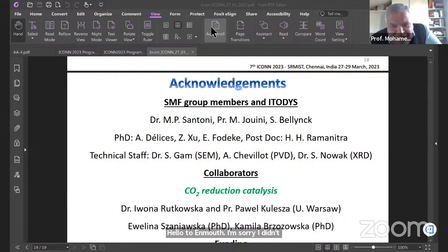Yes, palladium. We use palladium because this was a first work on this kind of electrode, and it was just a proof of concept. We can use any catalyst, but the only problem is to get these energy levels, as I showed you in my slides, because the dye has to transfer the electron to the catalyst. So you have to match the catalyst and the energy level of the negative dye. And this is not really very difficult because the energy level of the negative dye is high enough to transfer the electron to the catalyst.